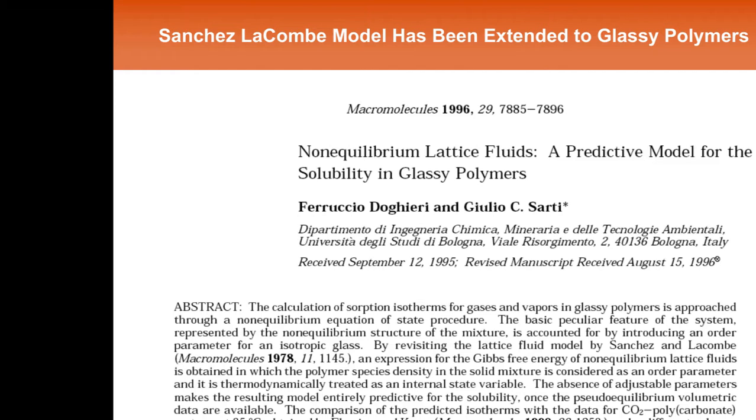And depending on how thin the sample of this material is, that equilibrium might only take seconds or fractions of a second to reach. And so what I mean by that is that the chemical potential of the penetrant inside the polymer can be exactly equal to the chemical potential of the penetrant outside the polymer if you have the polymer sitting in a bath of the penetrant. And at the same time, the material itself can be out of equilibrium. And so that's what's basically being said up here at the top.